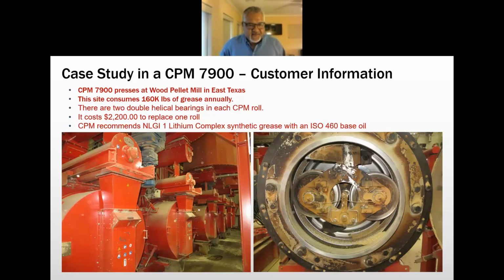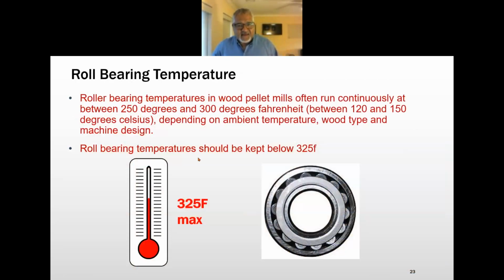I'll also go over their major competitors' lubricant recommendations, but CPM recommends an NLGI 1 lithium complex synthetic grease with an ISO 460 base oil. Well, okay, I know this is a high load application, but it's also pretty well sustained elevated temperatures. In this case, load is more of a factor in bearing life than temperature. But temperature is a factor. Temperature, load, and moisture content of the wood are also factors.